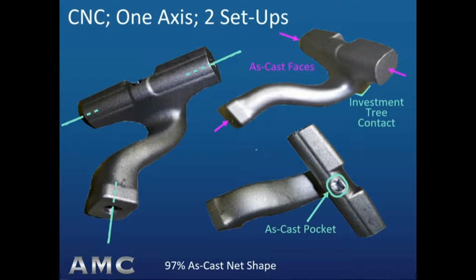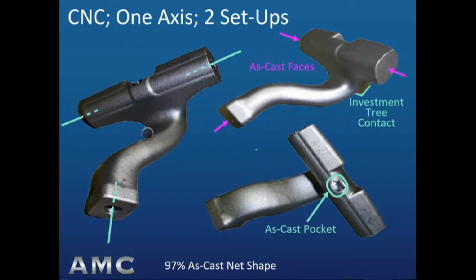It is a high alloy steel casting made in the ceramic shell investment process. It is machined in two single axis setups, one for a horizontal CNC and the other for a vertical CNC machining center. Like so many other investment castings, it is 97% as cast in final net shape. The accuracy and surface finish of the investment process enables the faces of the drilled and tapped surfaces to remain as cast. Those are shown in pink.